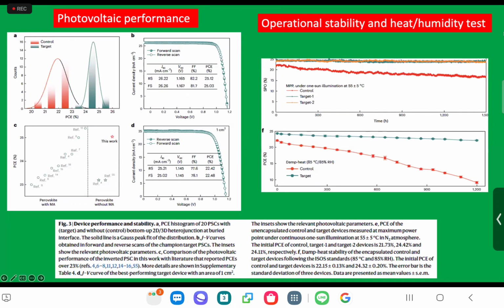The stability is excellent. MPP tracking shows hardly any degradation over 1,500 hours full light, and also the damp heat test is very good. I mean, it's less than 10% degradation over 1,200 hours. So, what is the amazing facet of this?